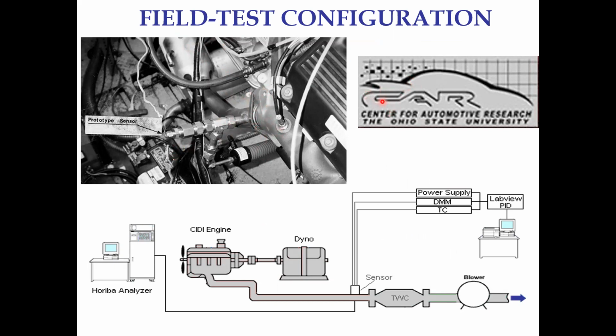So we actually ended up testing one of our sensor probes in a real automotive engine that is tested at CAR in our mechanical engineering. CAR stands for Center for Automotive Research. And this facility also comes with an on-board HORIBA analyzer that can help compare our sensor response with the HORIBA analyzer to make sure that we are measuring the right concentrations. And our sensor is positioned next to the lambda sensor. The temperature around here is about 600 degrees C.